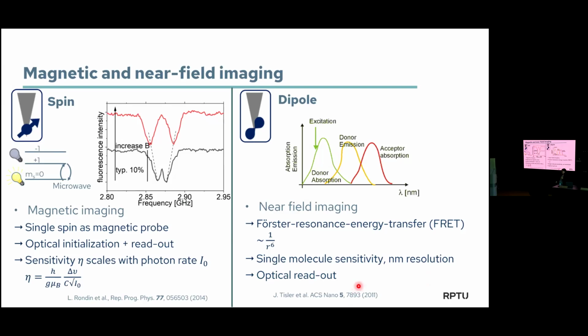And also there, of course, you need an optical readout, because when these dipoles exchange energy, it changes transition rates and then lifetimes change, and fluorescence changes. And this is why also here we need an optical readout. In essence, you need a donor dipole. You excite the donor dipole. Instead of radiating its energy, the donor dipole transfers its energy to an acceptor. In the results I'm showing you, the NV center plays the role of the donor, because often you want this donor to have the longer lifetime, to give it the time for this energy transfer before it radiates.